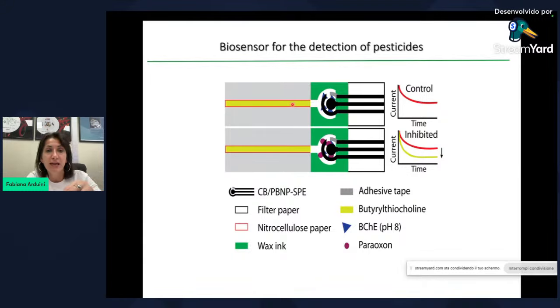So we preloaded the enzymatic substrate here, and we preloaded the enzymatic substrate here. And to make this measurement, we add only distilled water to dissolve the reagent and measure the initial enzymatic activity. And for testing the real sample, we add the real sample here in order to have the reaction between the enzyme and the inhibitor present in the sample. And when the solution becomes dry, we then add the distilled water to measure the residual enzymatic activity. If you observe a decrease of the response, it means that there is inhibitor within the sample.